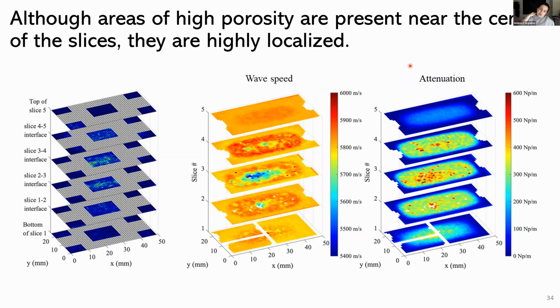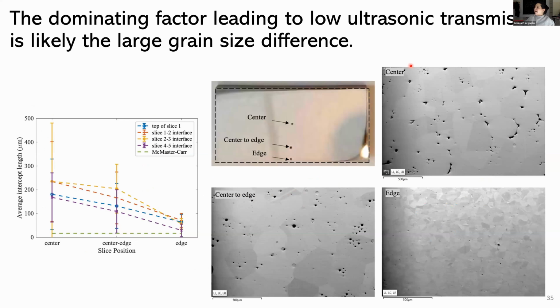Now, being someone that was trained in scattering in polycrystalline media, obviously our next thought is always to go to grain size, and that's exactly what we did. What you see was rather interesting, particularly in the context of what had been previously reported for binder jet samples. One of the widely cited advantages of binder jet was that you would get this uniform sintered structure, with small grains that were very well developed.